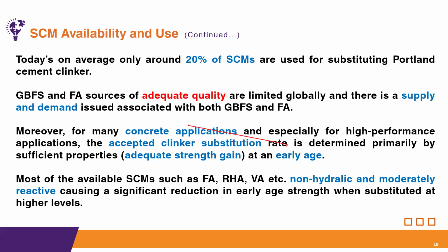And there is another issue. In most of the concrete applications, and especially the high performance applications, there is a limit on the clinker substitution, which is associated with adequate strength gain at early age. So if we replace these pozzolans at high percentages, there will be a problem in the early age strength of the concrete, which is required in some cases. Otherwise, it will delay the construction timelines, and there will be other issues also. Most of the available conventional SCMs, which are fly ash, rice ash, volcanic ash, are non-hydraulic and moderately reactive. So it is causing significant reduction in the early age strength when substituted at high levels.